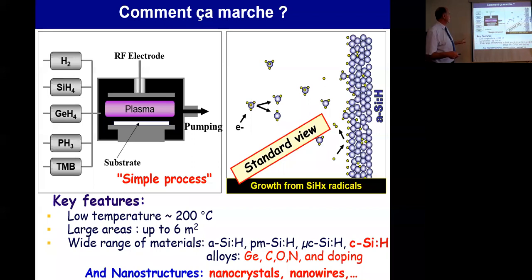We go to the plasma stability. So that's where I did my PhD and spent my life. Two parallel plates, you feed silane or germane or dopants, whatever. You make the plasma, meaning that you have collisions between electrons and the molecules. You make reactive species. These reactive species condense on the substrate, and you make a thin film. And if you are at low temperature, 200 degrees, most likely you're going to make a disordered semiconductor, amorphous silicon. But this can be done on large areas, 6 square meters of roll to roll. So it's flat panel. Flat panel displays come from this. Here you have an array of TFTs made of silicon.